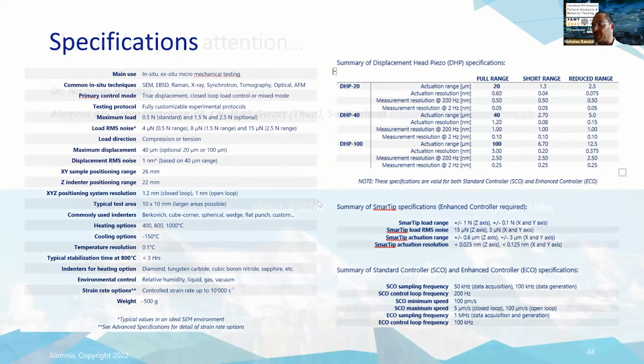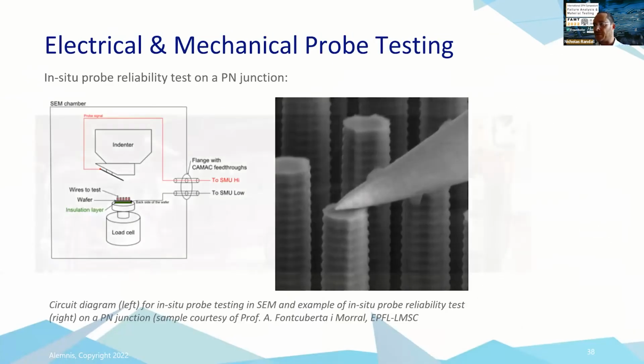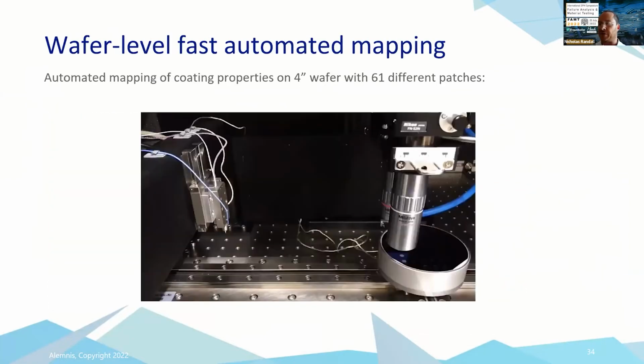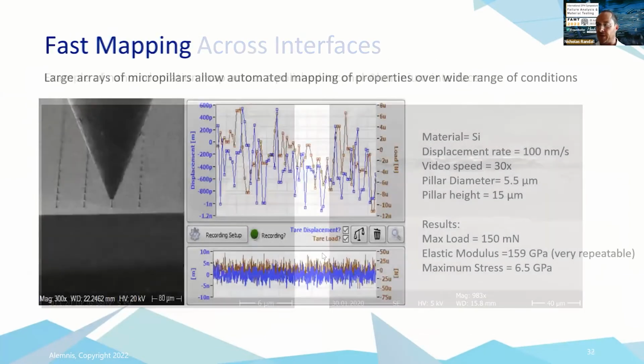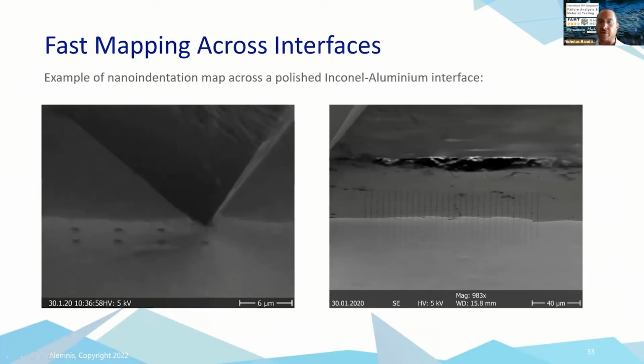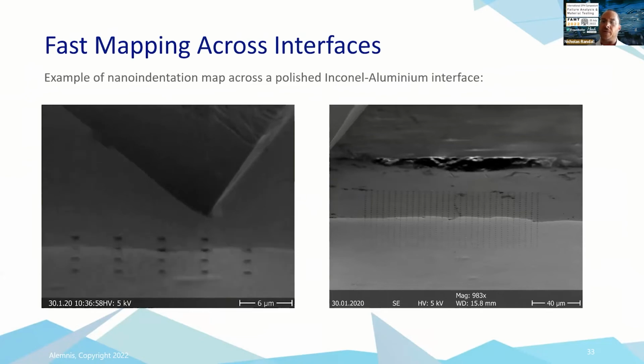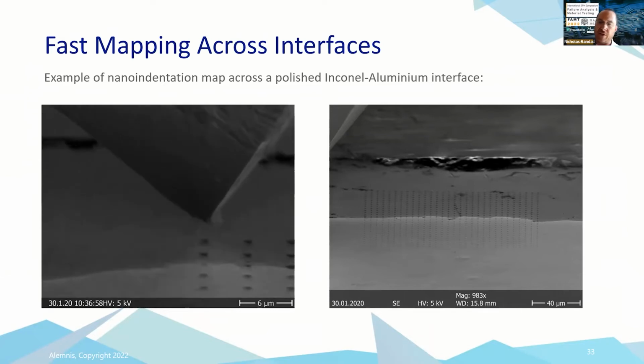Well, standard indentation, if I just go back to an indentation test. For nano indentation, we're using a Berkovich, which is a 3-sided pyramid. As you see here, this has an angle of 137 degrees, and the best tip radius you get on a Berkovich is about 10 to 20 nanometers. So even this pyramid has a radius at the apex. It's not the same as an AFM tip. You're never going to get the same resolution. But we need a tip area with a defined geometry so that we can calculate the contact area and therefore get mechanical properties like hardness or modulus. So it's a compromise.